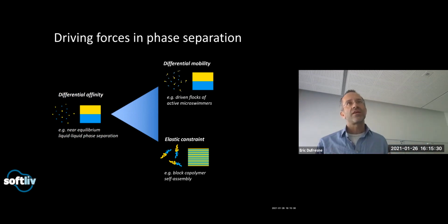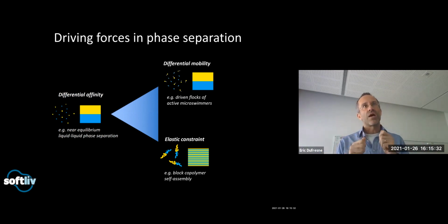The idea here is that when you have a polymer with two different blocks covalently bound at one spot, macroscopically those two blocks might want to be completely phase separated, but because of that microscopic constraint, they're not free to do so. And that elasticity enforces all sorts of really interesting morphologies in microphase separation.